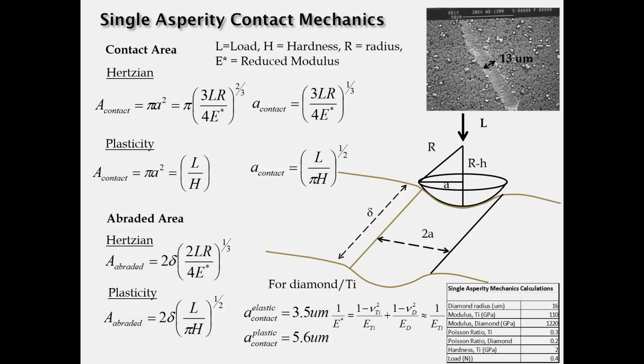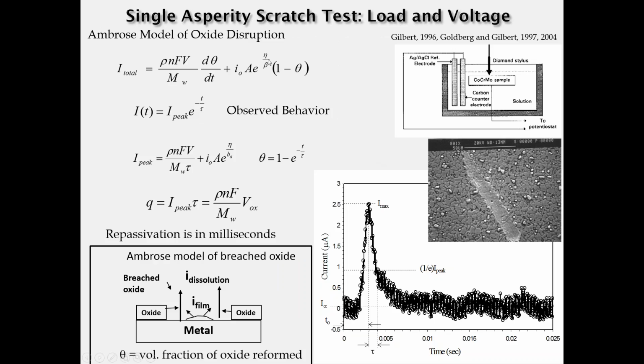understand the area abraded. Also, with the single asperity, we can look at the details of the repassivation reaction using a model that John Ambrose developed in the 80s that had two parts. One is the oxide forming, and the other is the ions generated. We know from measurement that this current response is somewhat exponential in a decaying fashion, and so we can solve that differential equation and learn about the charge associated with a single asperity scratch and how it's related to the volume of oxide that is reformed as a result of that charge.